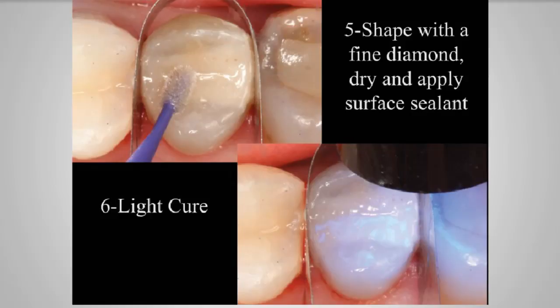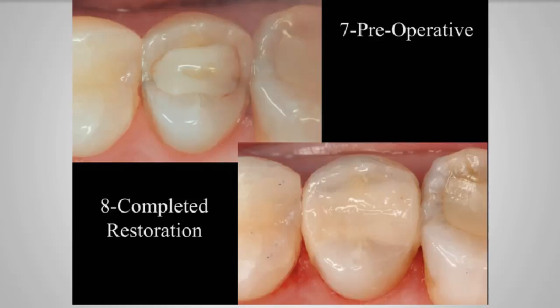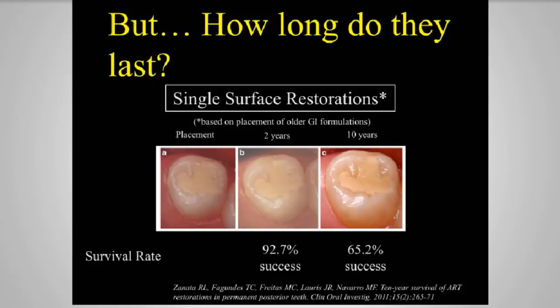Then when you're done, in this case I put a Tofflemire just around it and painted it on, and we light cured it. So there's the before, and there is the after. I think if we really thought about it, there are so many more applications where glass ionomer, though it does wear more than composite, might be a better restoration. It might be better because if I put composite in, obviously we'd have postoperative sensitivity. If we do a crown, obviously that's a good way to go, but we've taken away a lot more tooth structure. I look at these lasting for anywhere from 5 to 8 years at least.